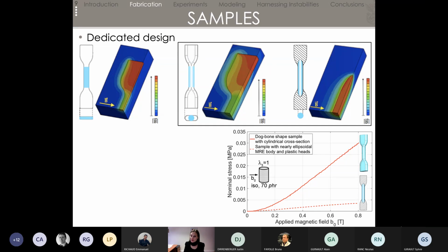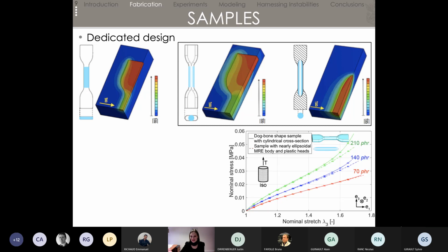The only problem that we have is that because we have a soft body stuck to rigid plastic heads, we have debonding. So now if I take the same two samples and do a tensile test, just a purely mechanical tensile test, when I plot nominal stress versus stretch, I can see that at some point the two curves are going to separate, and that's the sign that we have debonding between the body of the sample and its head.